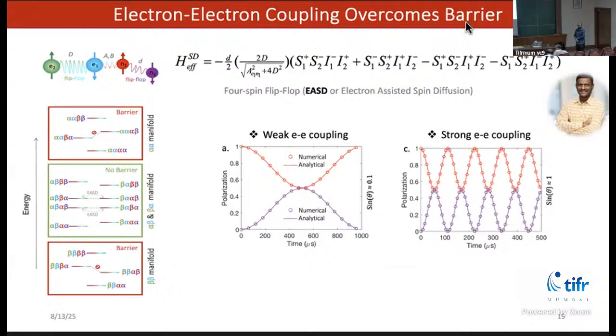Is there a parameter to look at how efficient the polarization transfer is, or how many molecules can be polarized? Is there a parameter to quantify that? There are parameters, but a lot of the time, many parameters are convoluted. So it's very hard to identify one problem. One can do numerical simulation and model it. Right. But something what Prajalak was asking about, how much fraction would you transfer? Since experimentally we don't measure the nuclei which are directly coupled with the electron. We measure the bulk magnetization. So experimentally, it's very hard to deconvolute different factors.